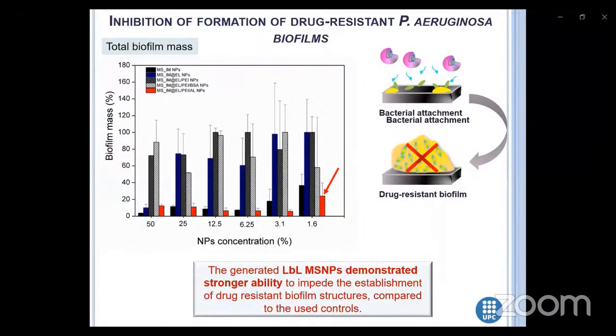So the ability of the developed nanoparticles to inhibit the biofilm colonization and biofilm formation was evaluated using 2 assays. Crystal violet assay was used to quantify the total biofilm mass. The drug-loaded nanoparticles demonstrated strong anti-biofilm activity due to the bactericidal activity of antibiotics and its burst release. Good biofilm inhibition properties showed the nanoparticles loaded with antibiotic and coated with elastin. The layer-by-layer nanoparticles with upper layer of polyethylenimine didn't inhibit the biofilm formation. The best biofilm inhibition activity was observed when alginate lyase was decorated on the layer-by-layer mesoporous silica nanoparticle surface.